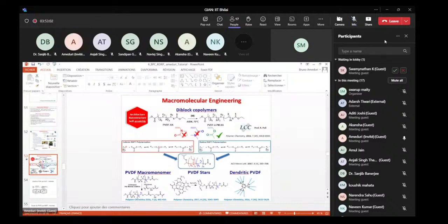It's a good question. I think that in the ionization effect, you have a lot of things which have been destroyed. And the idea of MALDI is to rebuild more or less the molecule. When I show different MALDI spectra, what happens is, if you work in negative mode, you will see a lot of fragmentation. But in positive mode, we have much better data in order to rebuild the molecule. For instance, VDF is stable, and we could see all the fragments separated by 64, which is the molecular weight of VDF. So if you do some MALDI in your investigation, please consider the positive mode and not the negative mode.